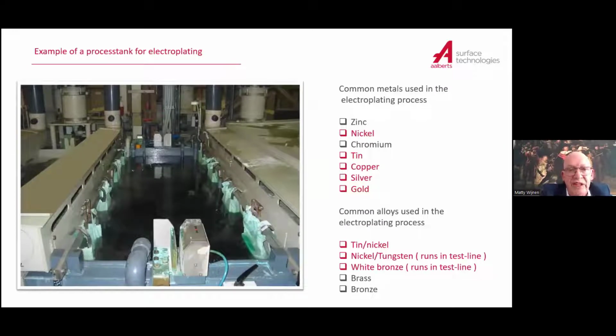Then you look here, on the left side, you see a plating belt, an electrolytic plating belt, to say it right. And here you see in principle the principles of that belt. On the right sides of the tank, you see the anodes, and in these bars, in these anodes, the metal which you want to plate is kept. That means that if I want to plate nickel, I have nickel on both sides of those bars, all of those bars. On both sides, the baskets are filled with nickel. If I want to plate zinc, the baskets are filled with zinc. If I want to plate tin, the baskets are filled with tin.